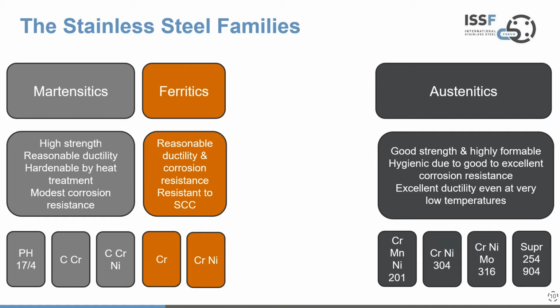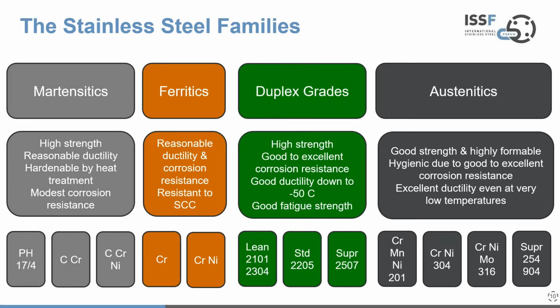And then we jump to the right of this, and this will become evident in a moment, with the austenitic group that most people are more familiar with, because you'll have come across terms like 18/8 stainless and 18/10 stainless, and maybe 304 and 316 as grade designations. These products have better strength, they're highly formable, they have good to excellent corrosion resistance depending on their alloy content, and they don't have a ductile to brittle transition as temperatures drop. So these are very much a utility group of stainless steels. But sitting in the middle are the new kid on the block, the duplex grades. I say new kid, they're still around 90 years old, but they're the newest family of stainless steels that combine the best of both. It's the best of the austenitics and the best of the ferritics, really.